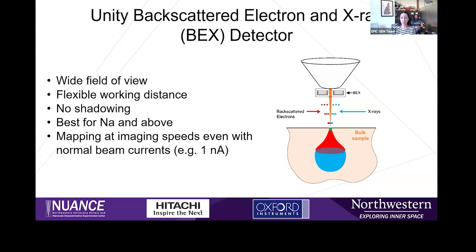Something like the mapping speed is on an order of 100 times faster. So you can also make large area maps much faster. What might have been an overnight map before maybe will take you a couple of hours now. This detector is mainly for mapping, so for quantitative EDS and more detailed compositional analysis, you'll still need to probably use the Ultim Max or Extreme, but luckily this detector can work simultaneously with the Ultim Max, so you can toggle between the two detectors, but not the Extreme.